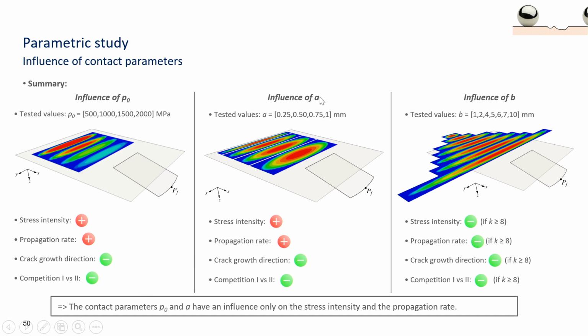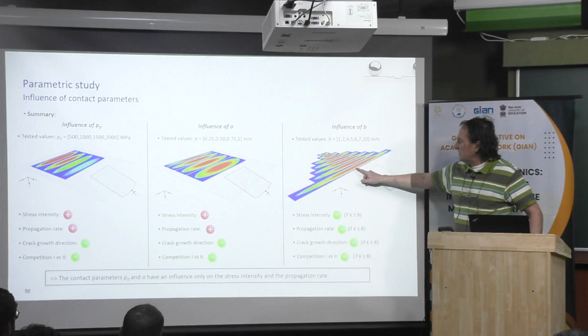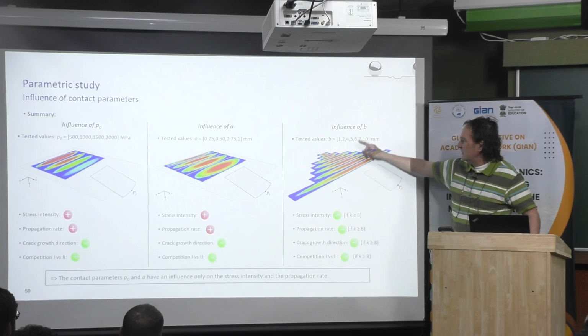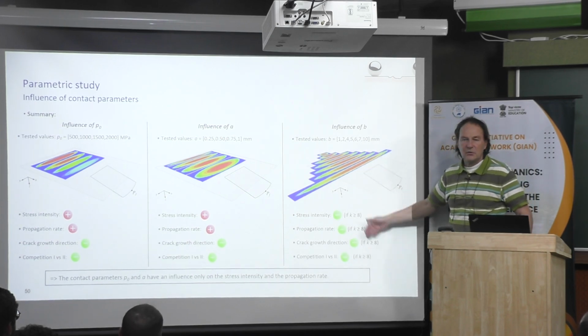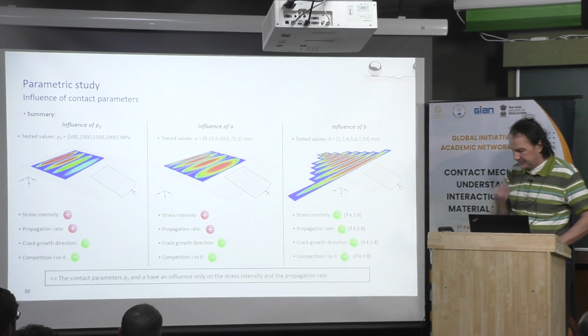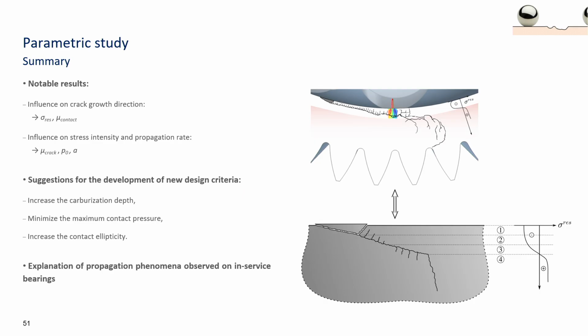When the semi-minor axis increases, it plays a role on the stress intensity factor, on the crack propagation, but again, it does not play a role on the direction of crack propagation, and there is no change on the competition between mode 1 and mode 2. And this time, when you increase the semi-major axis here, there is almost no effect on all the parameters. Okay. And then this way, we were able to predict roughly this type of crack.